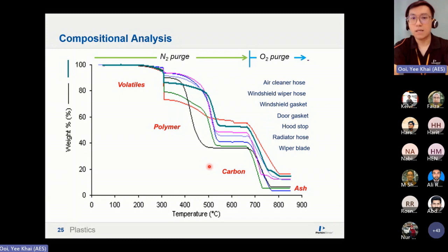So if you cook it up too fast at a very, very high temperature, what happens is it becomes char, okay? And that is actually carbon, a relatively simple form of carbon. So this is the thing that happens to your polymer as well. Your polymer will become shorter and shorter chain, simpler and simpler form, and usually it is carbon. And hence, if you do not have any oxygen, you are going to notice that the weight is getting more and more stable, but after that, when you run all your analysis, you'll notice that all your pan becomes black in color due to the carbon deposition onto your sample pan, okay?